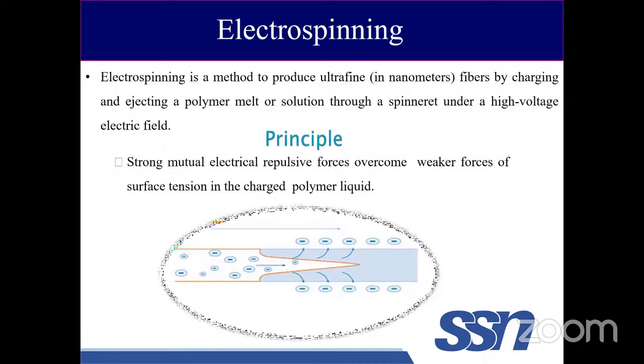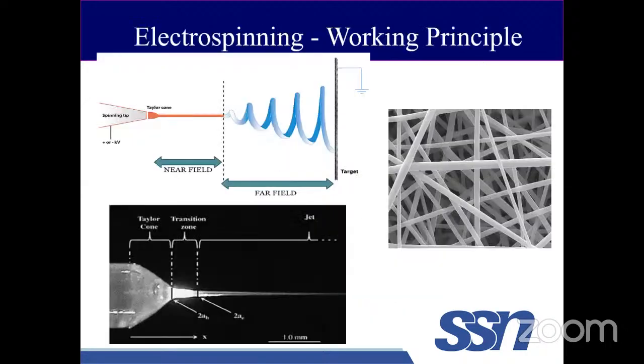Electrospinning is a technique which is going to produce ultrafine fibers via a charged polymer solution. We'll be having a syringe pump which is pumping the polymer solution via a syringe needle, where we will be applying a high voltage electric field, right? When we apply a high voltage electric field to this solution that is coming out from the syringe pump, when the potential exceeds the surface tension of the polymer, the polymer solution that is coming out from the syringe tip is converted to fibers, from solution to fibers, right?